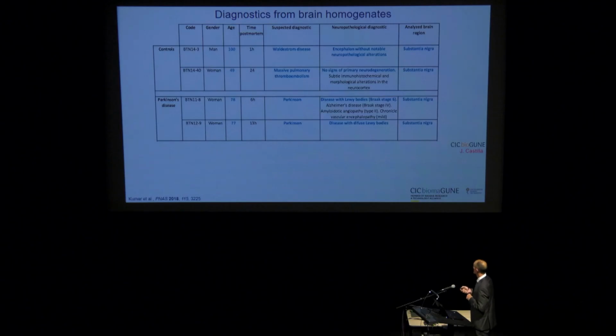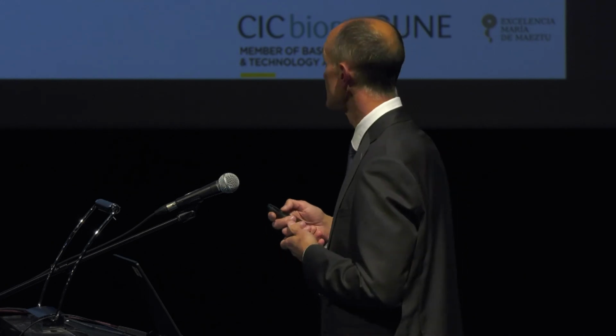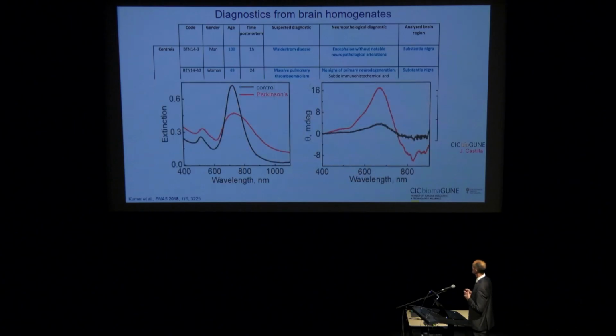And so by extracting the substantia nigra where these fibers are known to accumulate and doing some homogenization and then incubation with the nanorods, to our astonishment, we found that the 2 control brains led to almost no changes in the linear optical absorption, to sort of noise level circular dichroism, while the Parkinson's brains led to broadening and redshift of the linear plasmon absorption and much better defined circular dichroism.